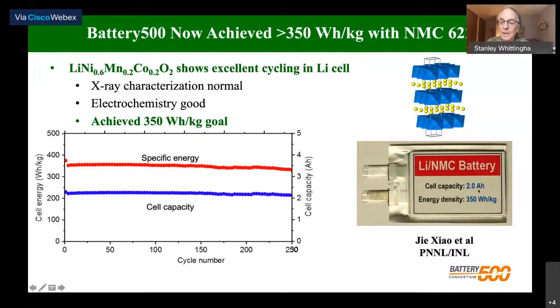And these are the typical pouch cells we use. After the cycling, we weigh the pouch cell and measure it, so we can calculate these energy densities accurately. So we include everything in this energy density, the pouch, all the inert material. Our target this year was 50 cycles at 350 watt-hours per kilogram. We've achieved that, so we hope to get to about 450 in a year's time. You can get to higher energy densities, but these are using pure lithium metal, so there are some potential safety issues if you go to a very large size.